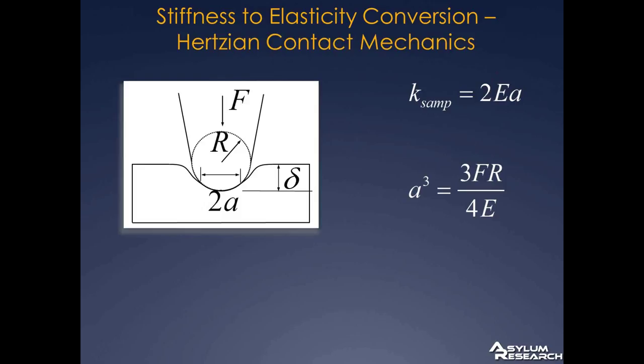So if you take this sharp point and you press down with a loading force, the tip of this point has a radius R, and it indents inside your sample a distance delta. Hertz derived this expression between the contact radius and the loading force, the tip shape, or the tip radius, and Young's modulus. So the promise here is that you have this very nice and simple relationship between Young's modulus and the stiffness that you measure.